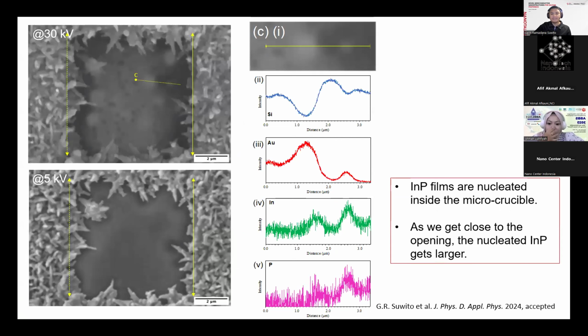Okay, so in fact, from SEM, we can find such gold islands in the double opening microcrucible, shown by the double arrows in here for the openings, and they are residing very close to the opening. So here, here, here, very, very close to the opening. First, we compare the images with high voltage and low voltage, at 30 and 5 kV. 5 kV obviously has a much lower penetration depth. So this is used to confirm that these islands are located inside the capping layers, because they were not seen anymore when we reduced the accelerating voltage.